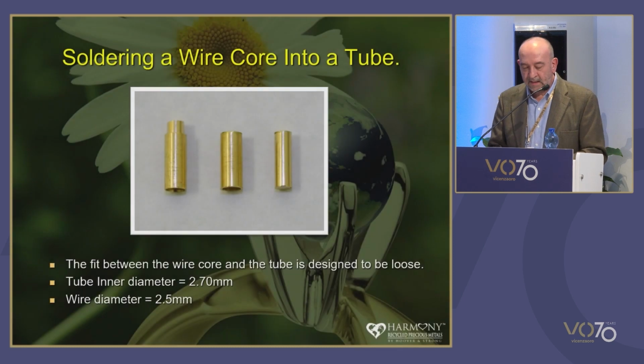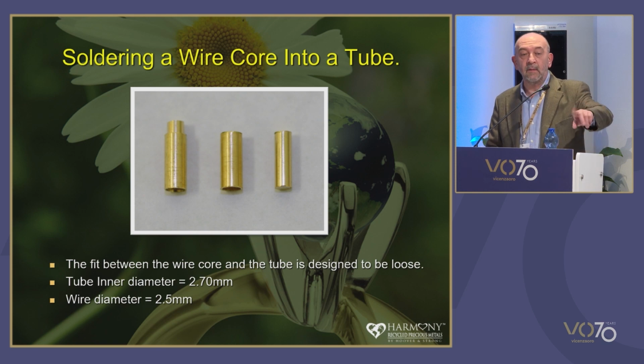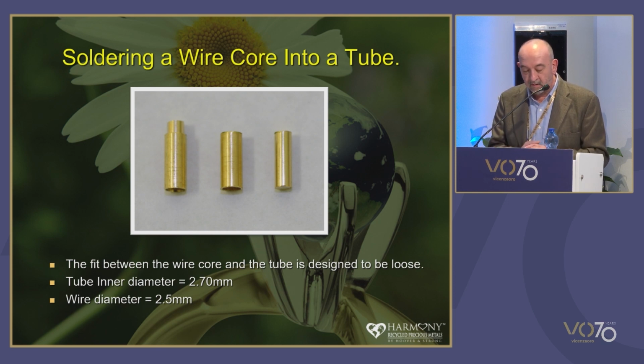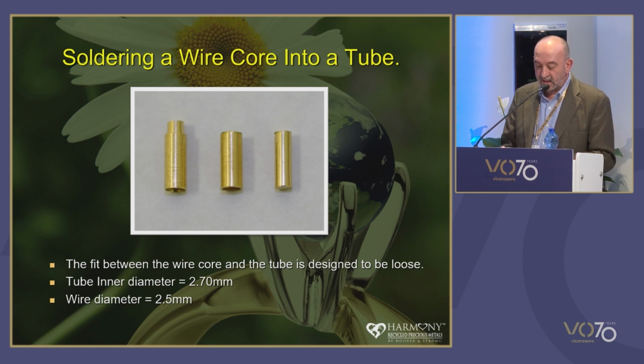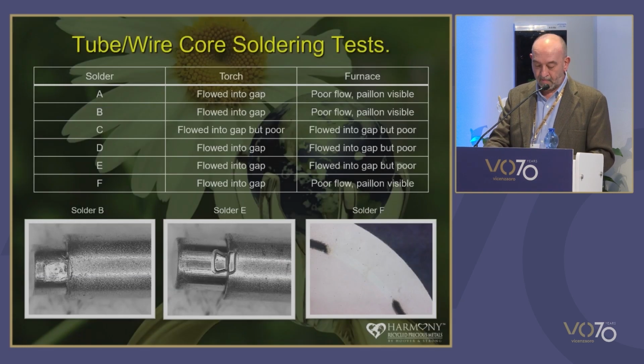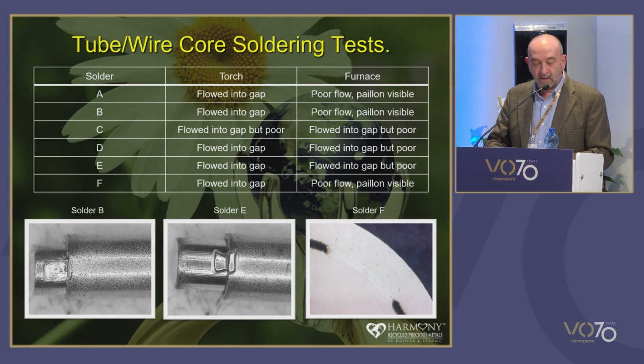So the final test we did was to put a core and solder it into a tube. As we can see the pieces here, we designed it to be a loose fit. So we had a tube with an ID of 2.7 millimeters, and a wire diameter of a very loose fitting 2.5 millimeters. And these are the results.